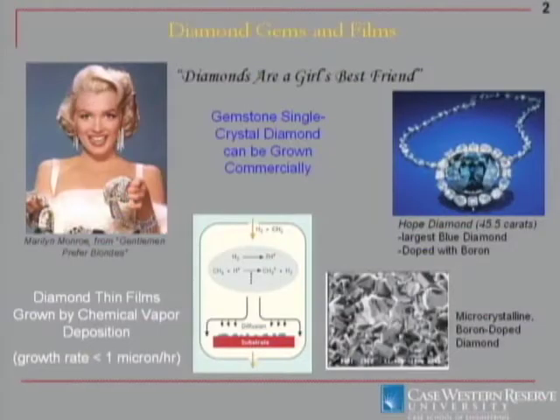Instead, what I do is grow diamond as a film, a different kind of film than Marilyn was involved with. But our method of growth is chemical vapor deposition, which is a vacuum method where you start out with a carbon-containing gas as what's going to be your source of diamond. The traditional route involves that carbon gas being diluted in a hydrogen atmosphere, and you activate the gas to break it down, and you're under the appropriate conditions to get diamond growth instead of other types of carbon like graphitic growth onto a substrate.